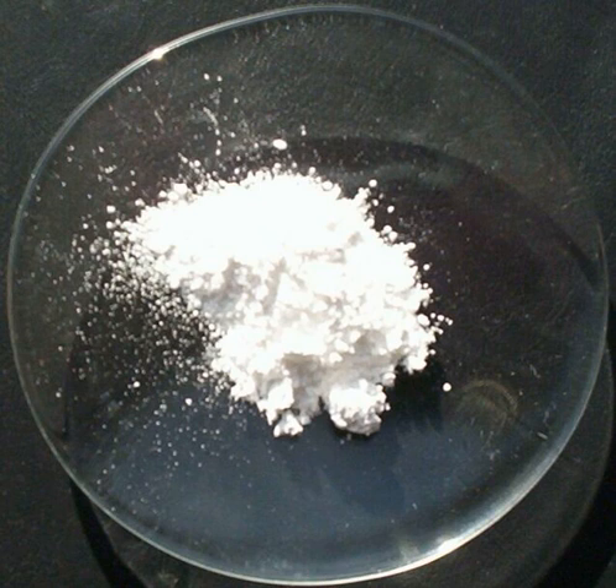MgO is also used as a protective coating in plasma displays. Magnesium oxide is used as an oxide barrier in spin tunneling devices. Owing to the crystalline structure of its thin films, which can be deposited by magnetron sputtering, for example, it shows characteristics superior to those of the commonly used amorphous aluminium oxide.